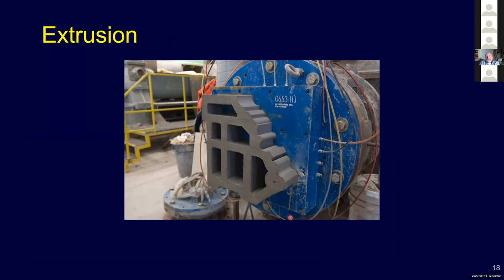Extrusion. Boston Valley is a master of extrusion, basically. You can see that this is a uniform cross-section, not necessarily simple. You have an auger type extruder, a screw extruder that's back here. And then that material, the clay, is fed in through the top, evacuated to take the air out, and then it's forced into a chamber with the auger, so it's continually pushing the clay in. And then it goes into the die, basically, and comes out as a continuous cross-section, okay?